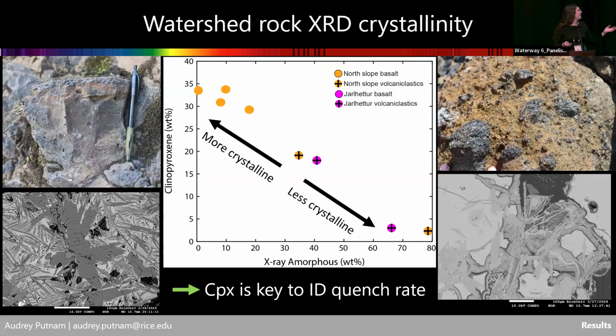And we can also see that in this case, clinopyroxene is very well correlated with the crystallinity of the rocks in our watershed. And that's because for this particular volcanic system, you only form CPX when you allow that remaining melt to slowly cool. And this gives us a cool tool to look at quenching rate in our watershed and how that is translated into downstream sediment.